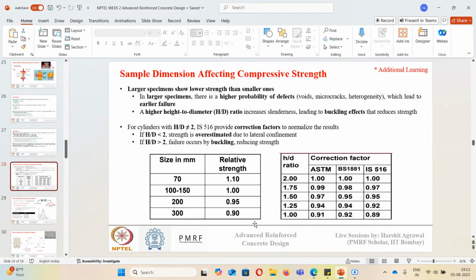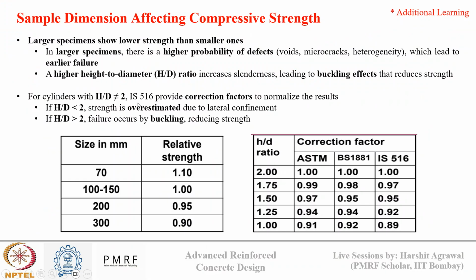I had this slide also, which I wanted to show. Larger specimens show lower strength than smaller specimens because of the higher probability of defects present in the system. And in IS 516, you can see the correction factors available for different sizes. This is for cube. For 70 mm, 100 to 150 mm, 200 mm, 300 mm, they have given different relative strength factors. Relative to a 100 mm cube, as we increase the size, the strength decreases. As we lower the size, the strength increases.